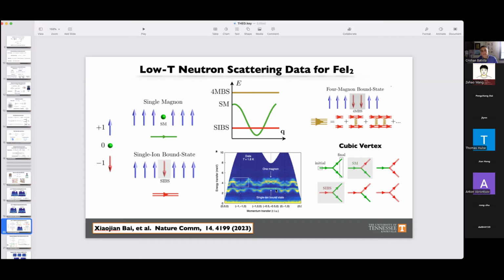So the bottom line is that here you do have two kinds of modes, quadrupolar and dipolar. They are hybridized. And moreover, you can even have bound states of two quadrupolar modes. This is what I'm trying to show here. If you consider two of these, they can also form a bound state. And this bound state formation is a non-perturbative effect. If you try to capture it simply with a loop expansion up to finite order, you will not get it, because it's a non-perturbative effect.